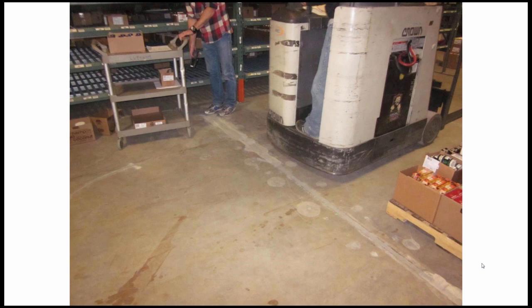And so the way that we identify these areas that need to have stabilization is if you have forklift traffic, you have a forklift driver on the building, you simply just look at these cracks and joints and you can see them moving up and down as the forklift drives over it. Having a very static, stable slab is really important to repair. It's probably the most important thing. Even if this joint was just moving a tiny bit, that would deteriorate over time. So it's really important to get them stable. And then, of course, when we're done with the repair, as a quality control measure, we have the forklift drive back over the top and make sure we've actually achieved the stabilization that we were intending.